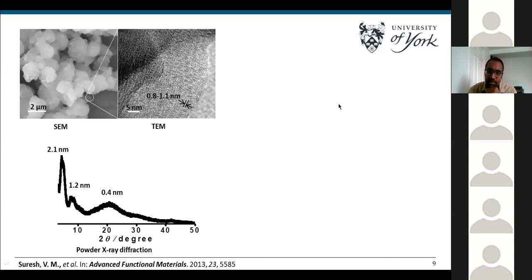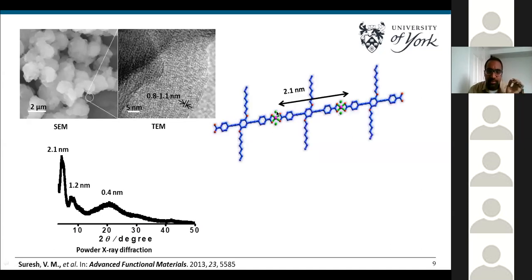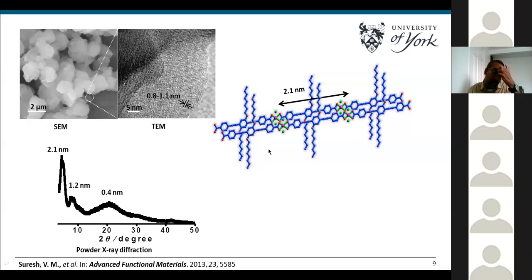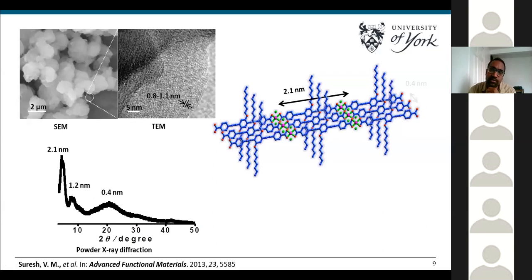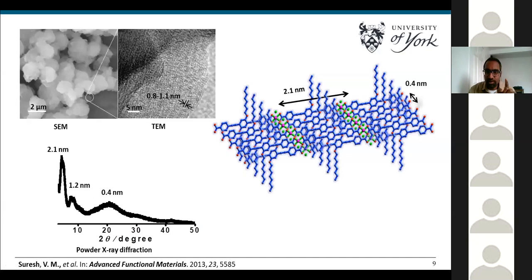Initially, the metal ion coordinates with the organic linker to form a 1D coordination chain, where the distance between the two metal centers is around 2.1 nanometers, seen in the first diffraction in the XRD. These coordination chains have a highly aromatic core, so they can interact through supramolecular pi-pi stacking interactions. These 1D chains start stacking to form a two-dimensional coordination polymer. Then these layers interact with the hydrophobic alkyl chains and create a three-dimensional supramolecular structure.